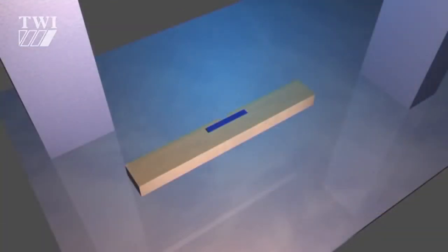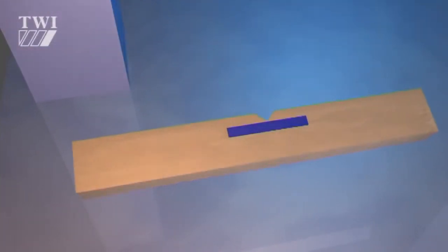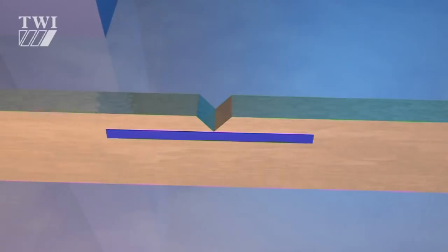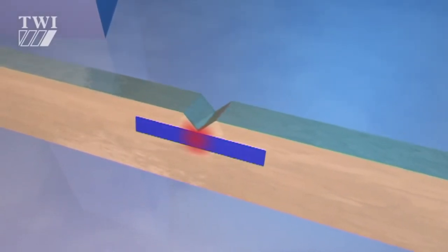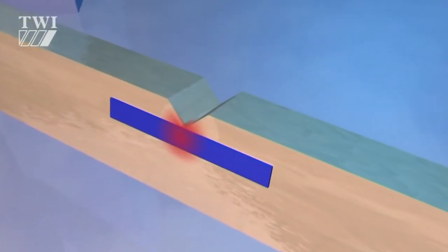Imagine a tiny element of the material across the tip of the notch. In effect, we have a minute tensile specimen. Under free conditions, this would behave like a simple tensile specimen, but this element isn't free. Its ends are anchored in regions of low stress, while its centre lies in the highly stressed plastic zone. The notch produces large plastic strains, highly concentrated at the root and constrained by large regions of relatively undeformed material.